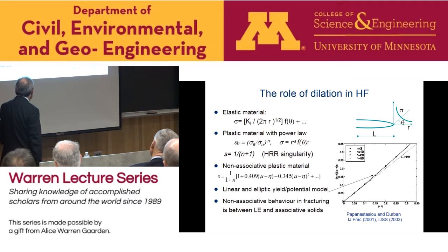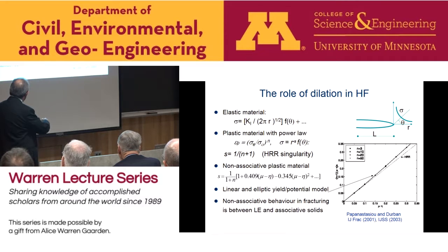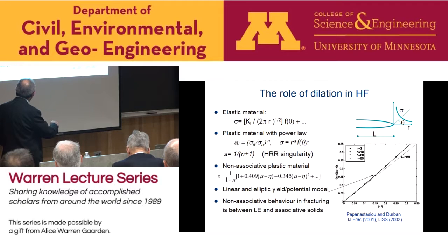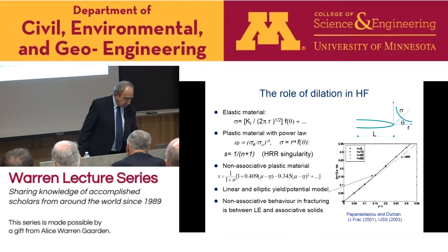For non-associative plastic material, we show in this work with David Durban from Technion, Israel, that the singularity is even weaker than the HRR. It is given by this form here. It's even weaker. And this mu minus eta expresses the level of the non-associativity, okay? The level of non-associativity. So basically, the non-associative case is in between elastic and associative case. And we show that also with finite element calculations.